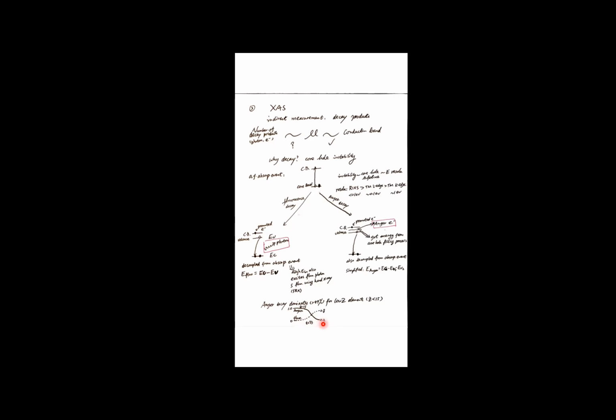As we go further down the periodic table and increase the atomic number, the Auger electron decay percentage is decreasing, and at the same time, the fluorescence decay is increasing. At some point, they have their equal share. And later, for the high-Z elements, the fluorescence decay is the dominant process. So this is a picture I hope we have in mind.